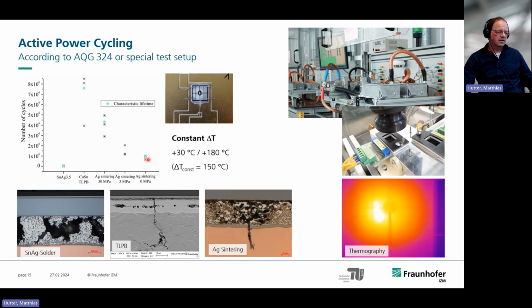And if you, instead of using no pressure during sintering, use a higher pressure of 5, or in this case 30 megapascal, you can achieve another factor of 10 in lifetime. So you see, if you compare the pressure sintered joints with the tin silver joints, you have a factor of 100 between the lifetime. And with this special test setup, even the copper tin transient liquid phase bonds survived even more on average, but we only tested 3 samples, so it's more or less in the same range as pressure sintered joints. And here you can see the test setup.